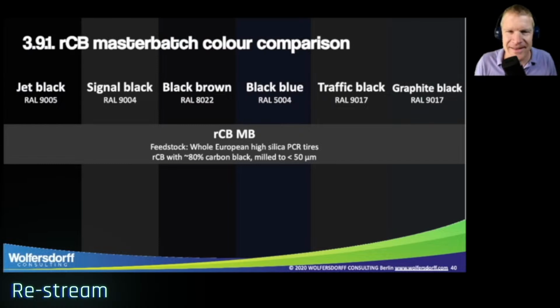Now let's put that again into the slide we had seen early on, and let's compare how black this recovered black master batch really is. And we can see it's not quite black because it is a gray pigment rather than a black pigment. The ash content, we could consider the ash as a white pigment. So it's a mixture of a black pigment and a white pigment. And this is because this particular recovered carbon black was made from European tire feedstock. Furthermore, European car tire, PCR, passenger car radial tire feedstock, has a high ash content because it has a high silica filler content in the tread. The RCB has only 80% carbon black. Also, I don't think it was milled very, very finely.